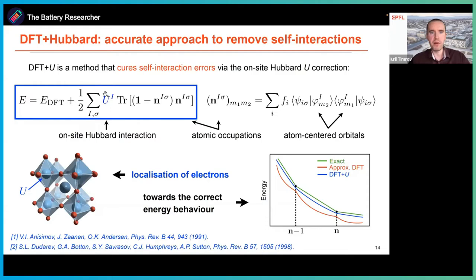Then we have the trace of 1 minus n times n, and n are atomic occupation matrices that depend on atomic index, spin, and magnetic quantum numbers m1, m2. They have a simple definition. We sum over states labeled I, f_i are Fermi-Dirac distributions, psi are Kohn-Sham, or if you want, Bloch wave functions, and phi are atom-centered orbitals. These atomic occupation matrices are useful because by taking the trace of this matrix, we can tell how many electrons are sitting on the 3D shell of iron, for example. This correction is very simple, but it depends on an external parameter U, which is in principle unknown. But I will talk more about this in a while.